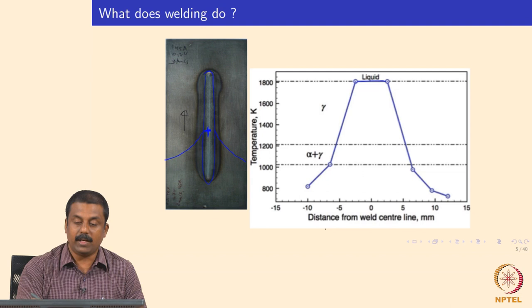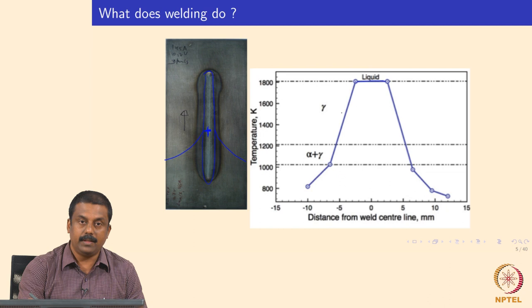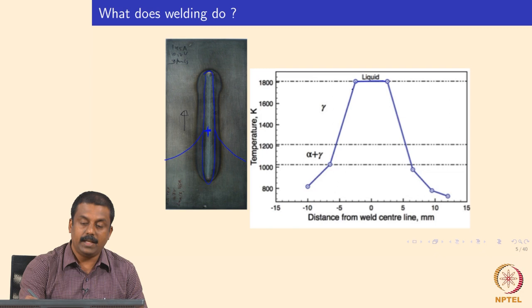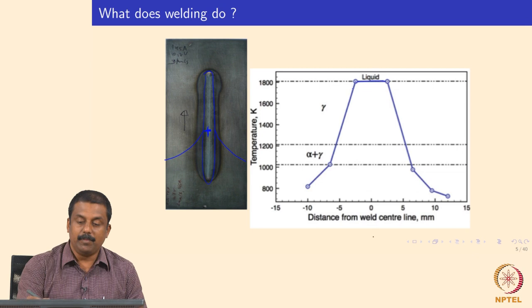Looking at peak temperatures based on the phase diagram: when the temperature reaches above the A3 line, you have complete austenitization, and then the heating and cooling rate dictates the amount of austenite formed. If the temperature reached is much higher, even with very fast heating rates, you may have a fully austenitic microstructure and subsequently cool back to a fully martensitic microstructure. Moving away, the peak temperature can also fall within the intercritical annealing region in the heat affected zone.